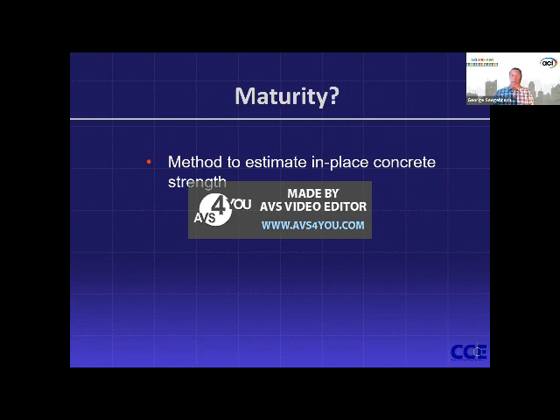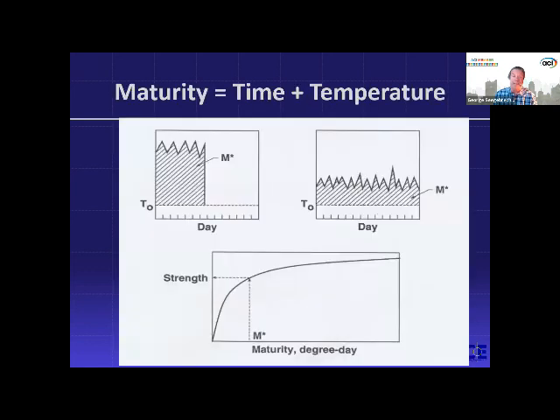So maturity is a way to estimate the in-place strength of concrete, and it is a time and temperature-based test in ASTM C1074. Being an exothermic reaction, in warmer temperatures the strength obviously develops quicker, and in colder temperatures that becomes slower. It's kind of like baking. On the left, if the temperature is high, we achieve our maturity goal, which would be the area underneath in the hash there, very quickly, like a microwave example. And in the next one, let's say you're baking something at lower temperatures, but for a longer amount of time, and then our concrete comes to maturity.